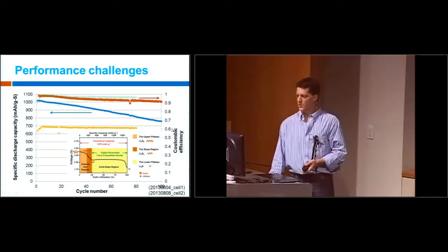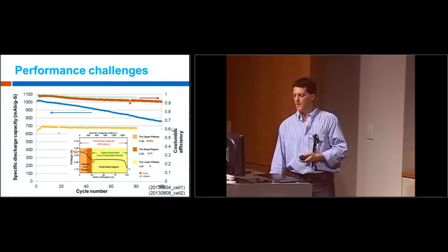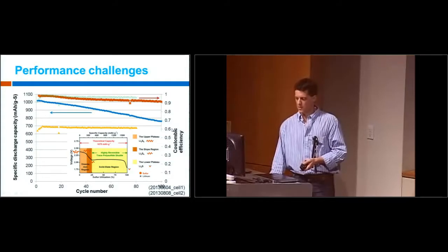So one of the other strategies, if I come back, this is the discharge curve again. When you start here with the elemental sulfur, you start at around 2.3 volts, and the first change is that you lithiate that sulfur, and it's in the form of lithium polysulfides, but dissolved. Then you come down here to another solid state region where you're basically converting lithium sulfide species. So if I hold the battery and cycle it within this range, there's essentially no liquid. It's all solid state.